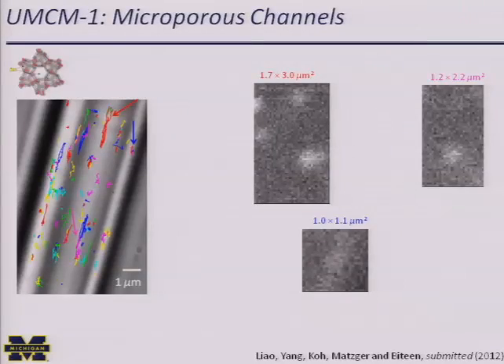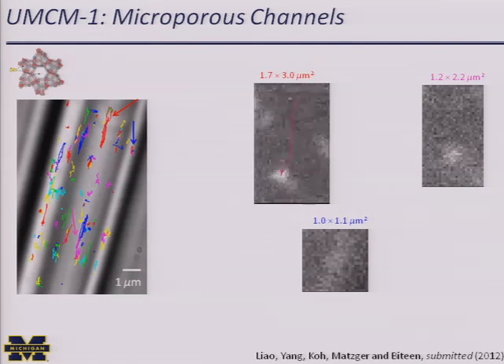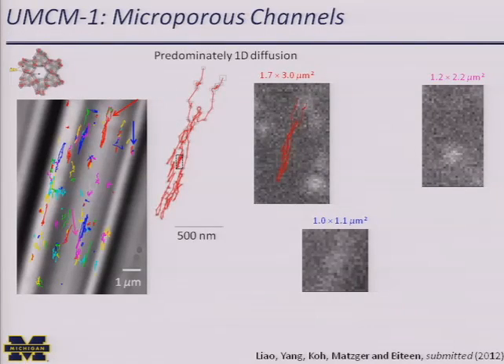We can look a little more in depth at the tracks. And so here I'm showing only trajectories that last half a second or longer. And there's a few different modalities that are seen. So this red one here is a primarily linear track. And so if we watch it here, we see this molecule that's going up and down. It's moving in 1D, but you also see that it's jumping somewhat from channel to channel. So we see this structure where there's motion along channels, but also maybe some jumping to other channels. And this black is showing us a region where, for a small amount of time, there's some confinement.